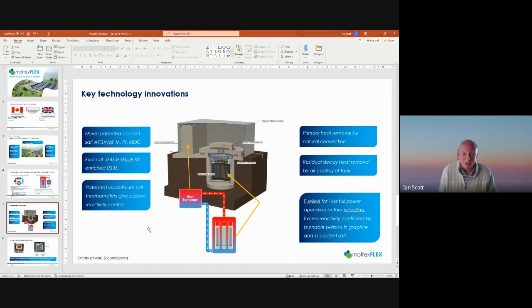It's basically cryolite from the aluminium smelting industry, an aluminium fluoride, sodium fluoride mixture, high melting point, which means the reactor has to operate at high temperature, and it does. We're looking at about a 770, 790 degrees centigrade output temperature. But it's an extraordinarily good coolant. It has brilliant thermophysical properties, very high heat capacity, is neutronically very attractive. It's an excellent coolant, a joy to work with as a chemist.